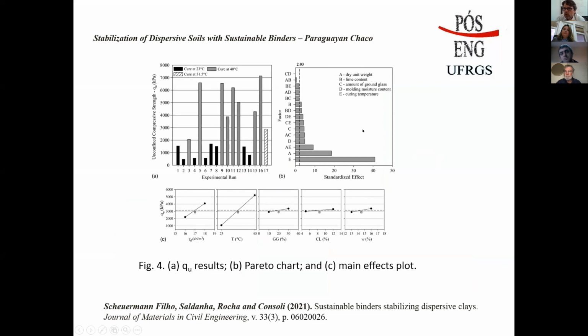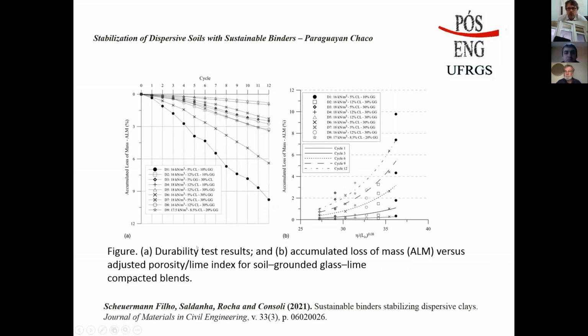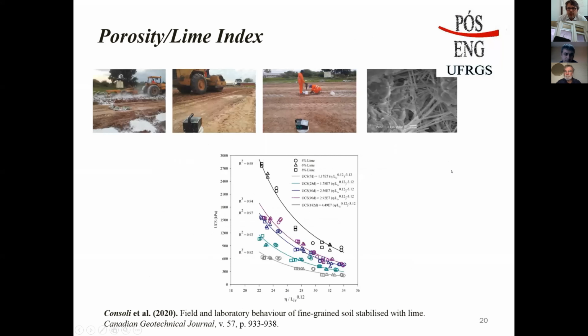So by introducing some kinds of residues, specifically one, if you know what you are doing chemically, you can improve the material, and that kind of problem is not going to happen anymore. This was published, as I said, in 2021 already. You can see it on sustainable binders stabilizing dispersed clays, specifically in this case. Here is a continuation of it, showing the durability effect, how it works, and so on for this case. This is also something quite interesting: we have carried out some tests in the field with this material and also in the lab.